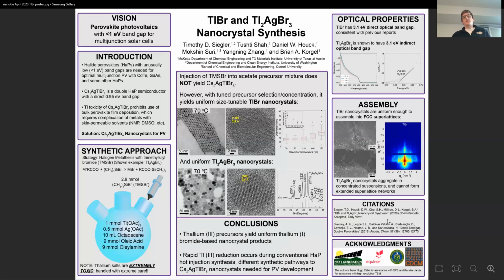Recently, however, the Karuna Dasa group at Stanford University has developed a synthesis for a single crystal of cesium silver thallium bromide, a double halide perovskite which exhibits a direct 0.95 eV band gap. While this is very exciting and could provide an answer to this conundrum, the acute thallium toxicity of cesium silver thallium bromide means the traditional spin coating and solution